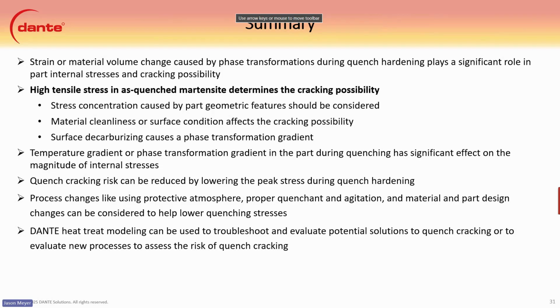Material cleanliness should be considered, or surface condition effects on the cracking possibility. So if you have inclusions or porosity in any way, those can affect cracking because they're good stress risers. Surface decarburization was shown to have a big effect on the phase transformation gradient. The temperature gradient or phase transformation gradient in the part during quenching has a significant effect on the magnitude of those internal stresses. Quench cracking risk can be reduced by lowering the peak stresses during quench hardening. Process changes like using a protective atmosphere, proper quenchant and agitation, and material and part design changes can be considered to help lower the quench stresses.